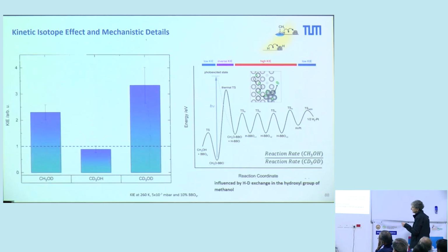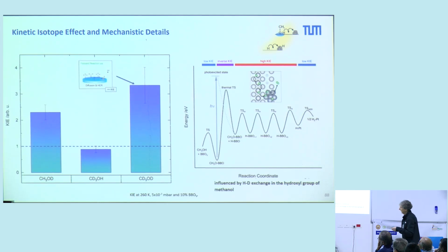And here are our results. And you see indeed that we have the highest isotope effect for CD3OD. That means it is indeed this diffusion of the hydrogen that is relevant in this process. If you look at the other isotope, you see that the CD3 has a much lower kinetic isotope effect. This is consistent with this picture here, because this is formed by the photo process. We have a lot of photon energy, so the differences are negligible. And here, for the rate determining step, of course, we have a small isotope effect.